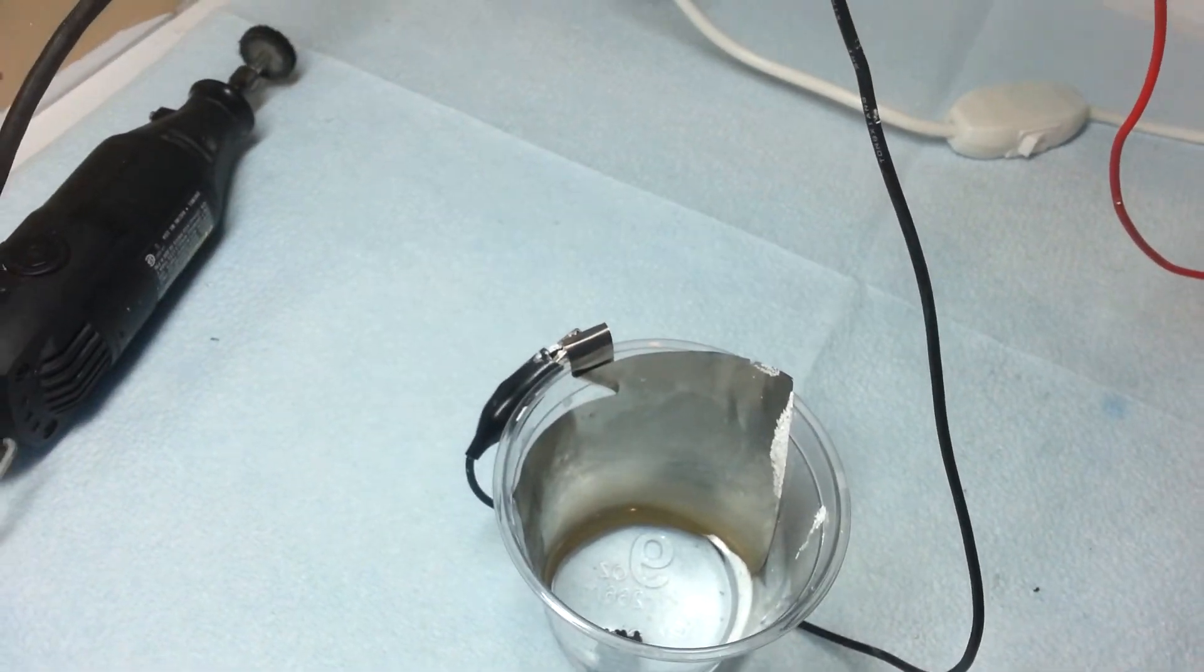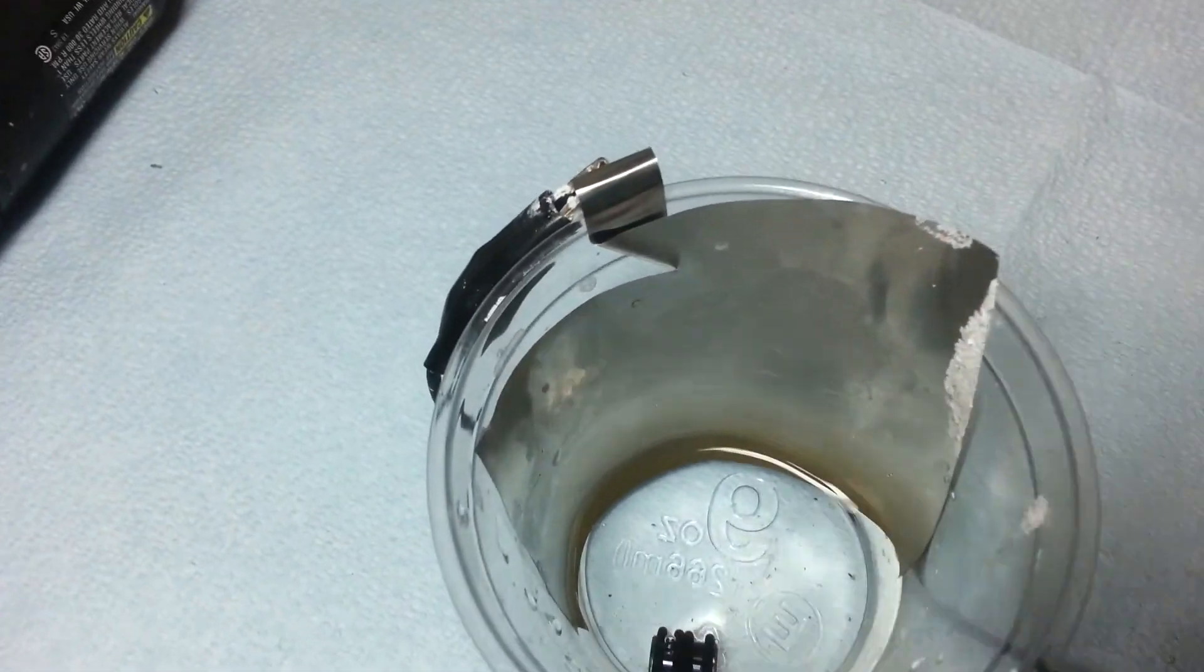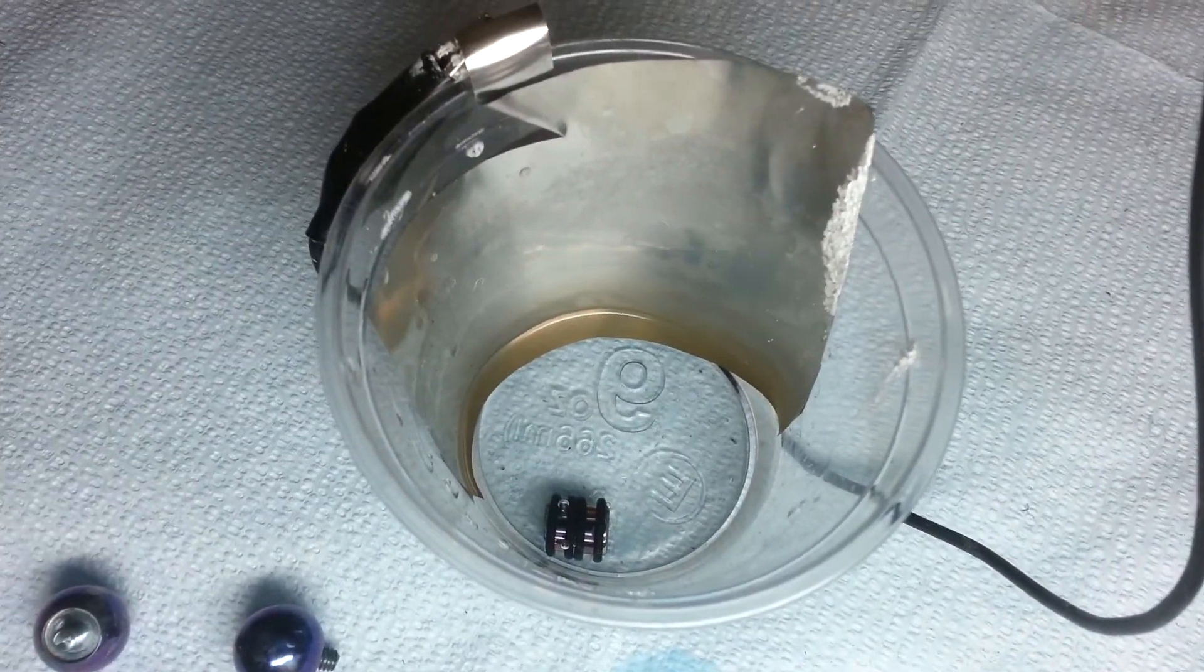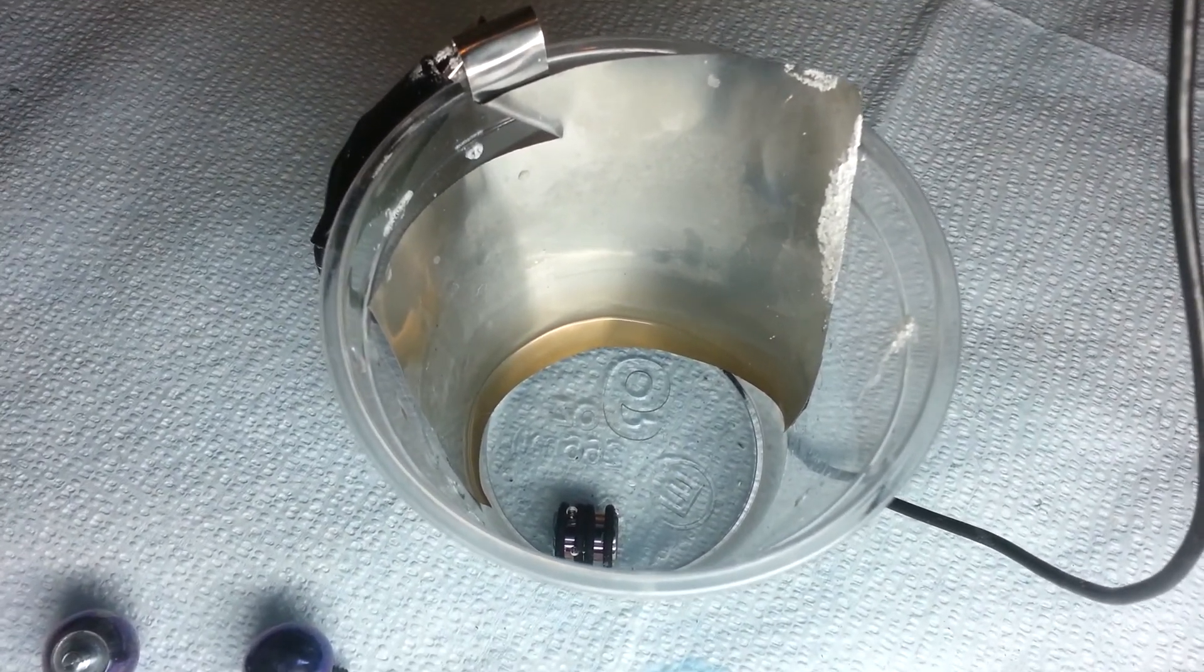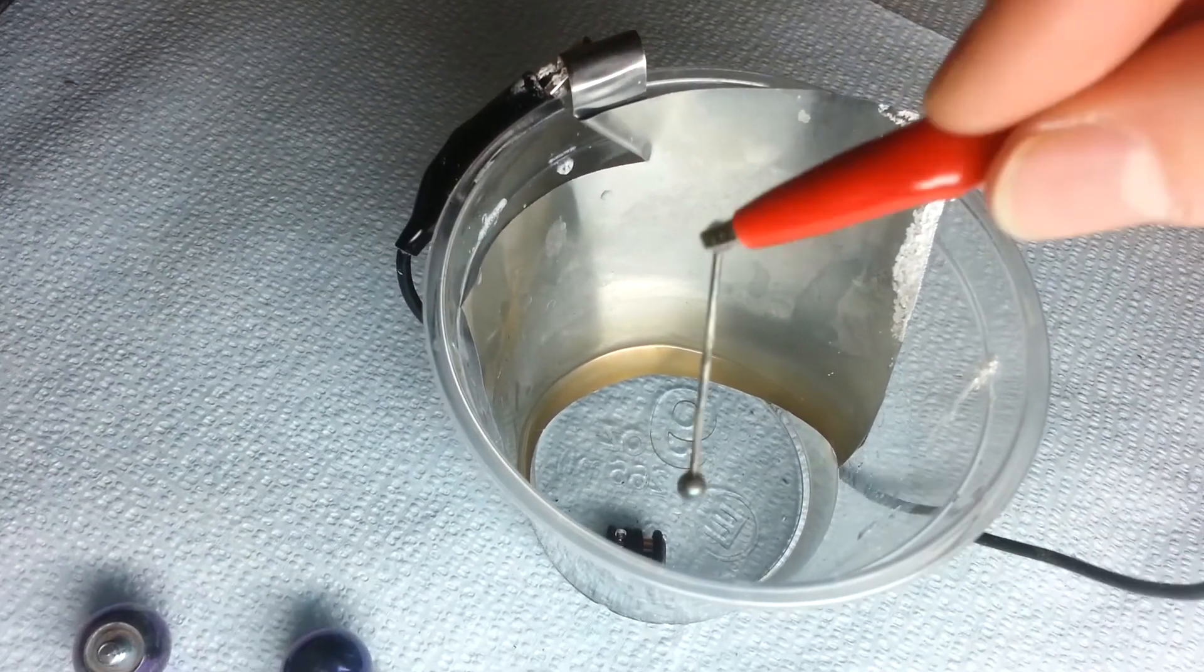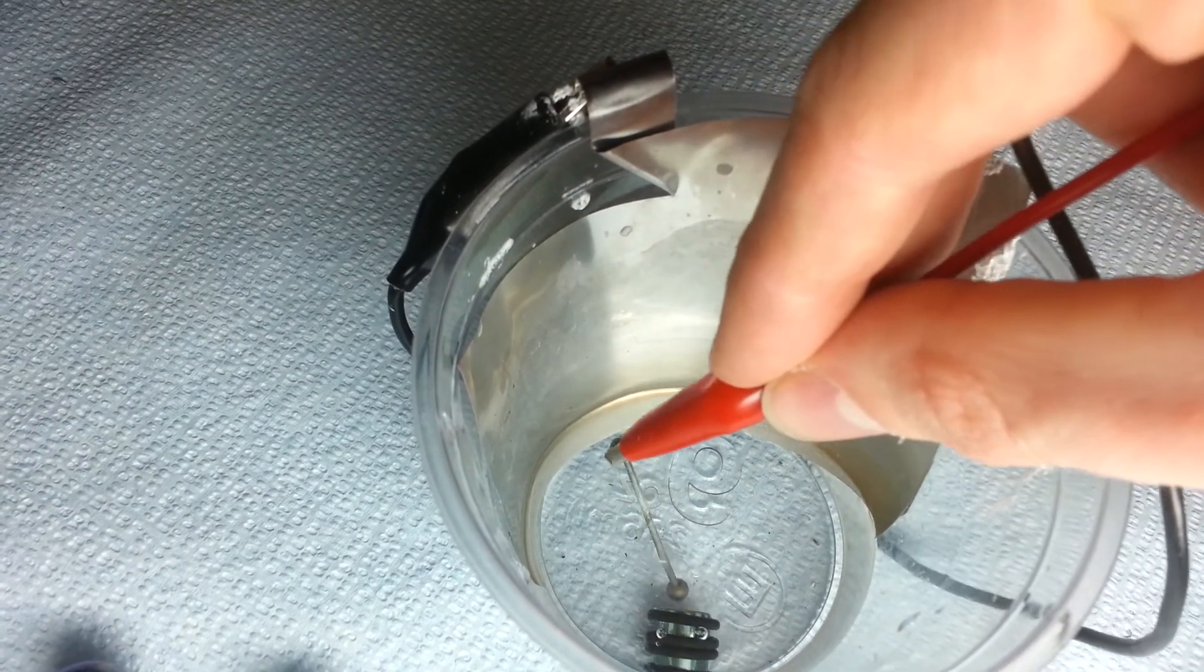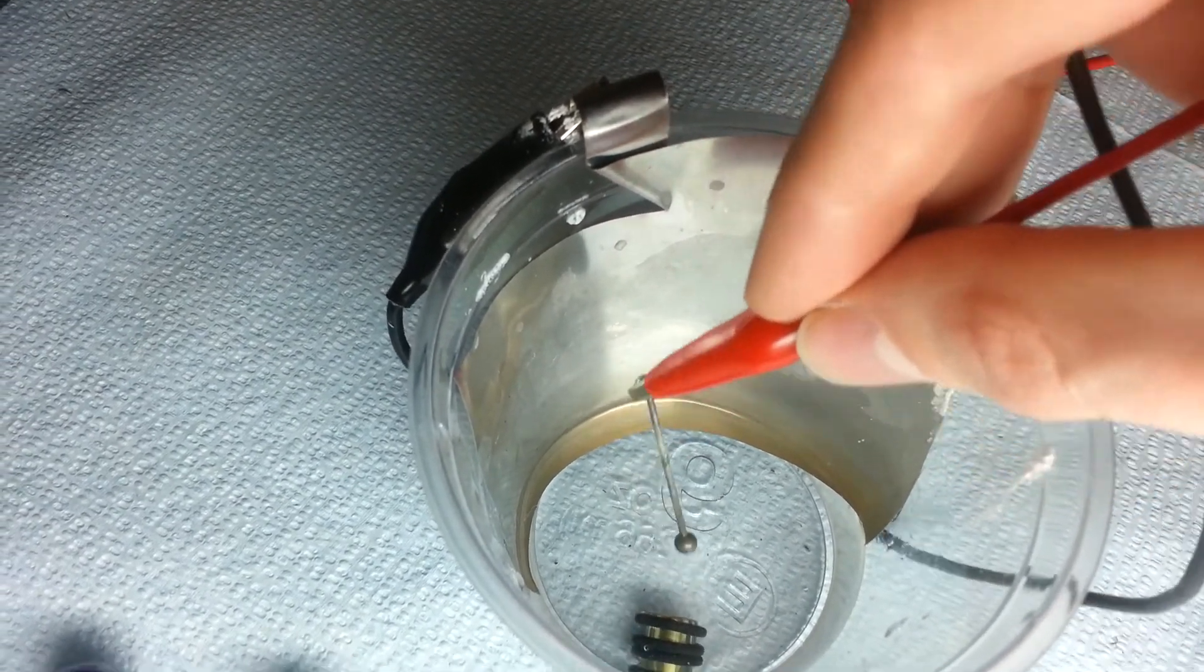This time I'm going to bring it up to about 63 volts which gives us a nice yellowy color. I'll figure out a good way to see this here. Alright. Sorry about the quality here, I'm shooting on my cell phone. Alright, anodizer is at 63 volts. We're going to go ahead and tap the jewelry.